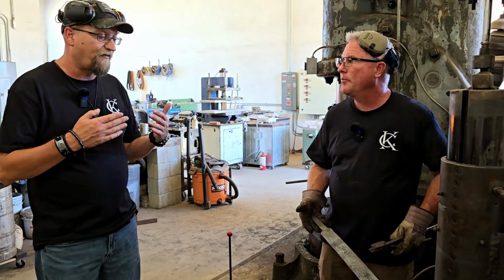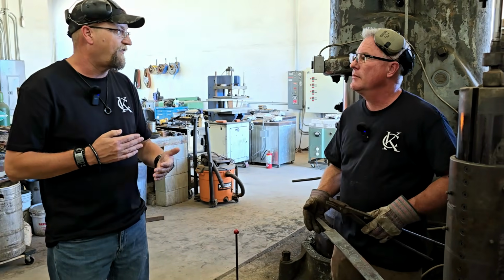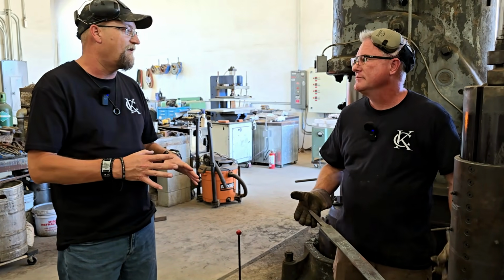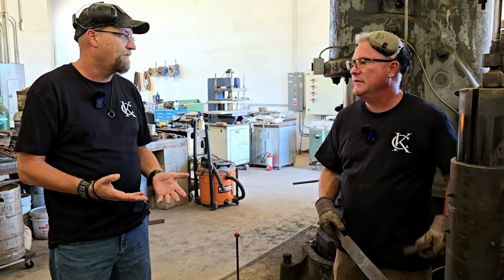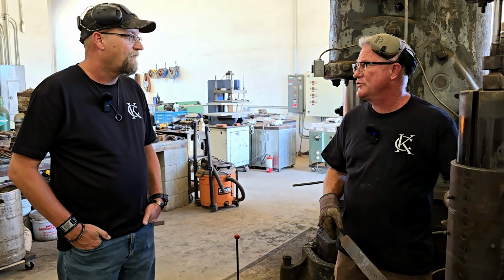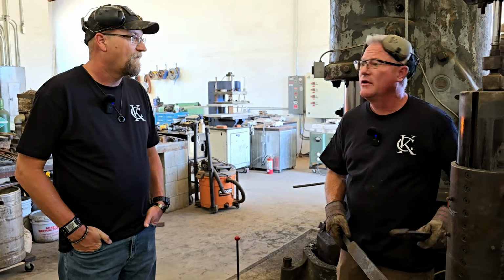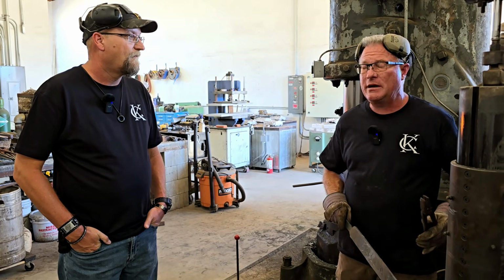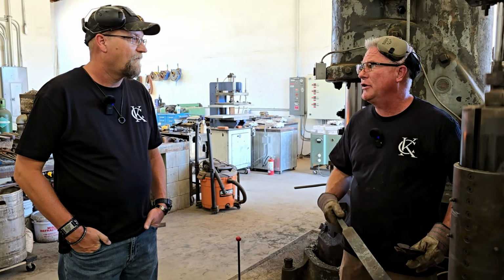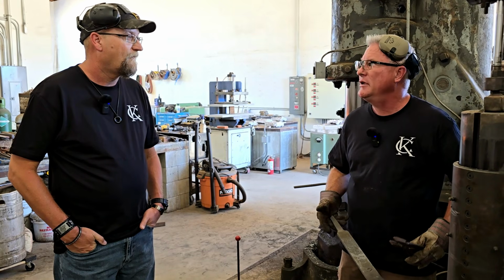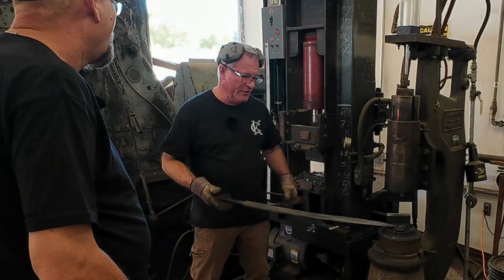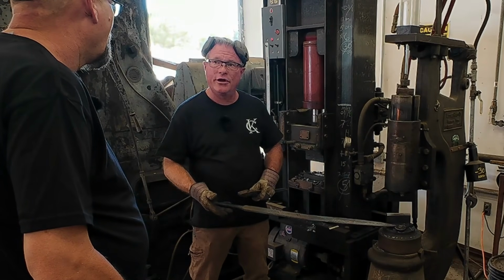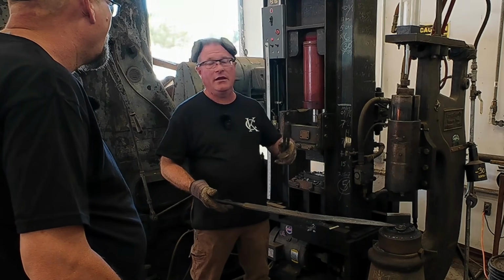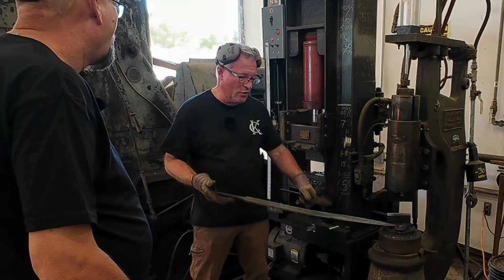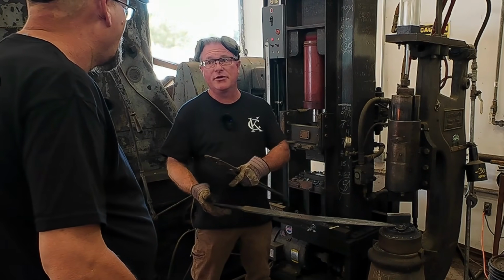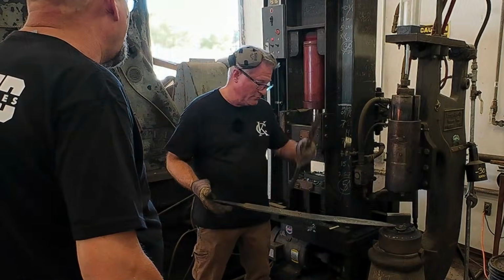So does that stage effectively erase everything that's been put into the steel? Yes, exactly. And you just maintain the shape? Yeah, maintain the shape, fix the grain structure that you screwed up in the forge and under the hammer. It's the same thing industry does. They've been doing it for 100 years plus. Fix that, then you go to the hardening process. In my case, in a lot of cases, I'll take it from rough forge like this right to the grinder. Well, could we see you grind on a blade? Yeah, absolutely.